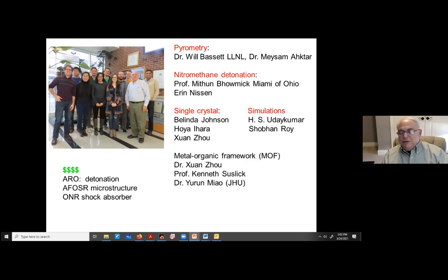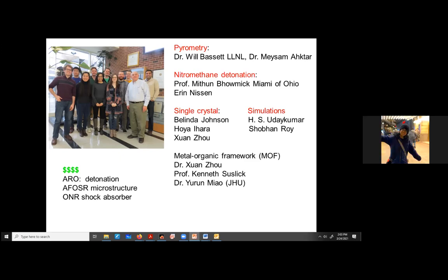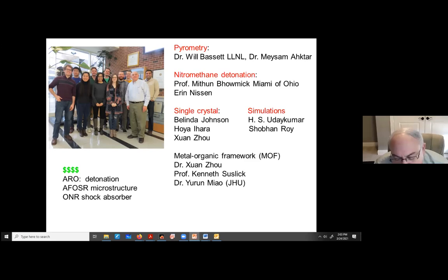Oh, okay. So the deal with a hotspot is that they're fleeting, they don't last forever. They die out if they lose heat faster than they propagate. When you've got such a tiny one, you've got a really high surface to volume ratio. My friend Craig Tarver at Livermore did a bunch of calculations. Basically, if it's a real teeny hotspot, it has to be really hot if it's going to live, and if it's a larger one, it can be cooler.